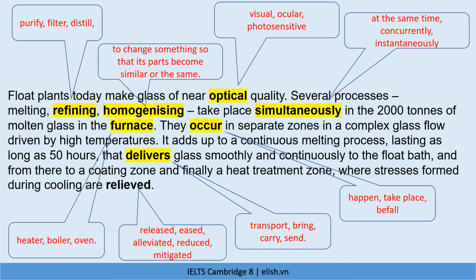Float plants today make glass of near optical quality. Several processes, melting, refining, homogenizing, take place simultaneously in the 2,000 tons of molten glass in the furnace. They occur in separate zones in a complex glass flow driven by high temperatures. It adds up to a continuous melting process, lasting as long as 50 hours, that delivers glass smoothly and continuously to the float bath, and from there to a coating zone and finally a heat treatment zone, where stresses formed during cooling are relieved.